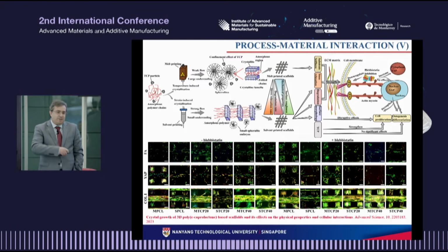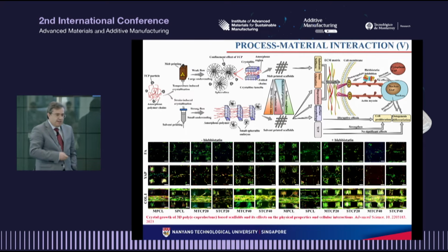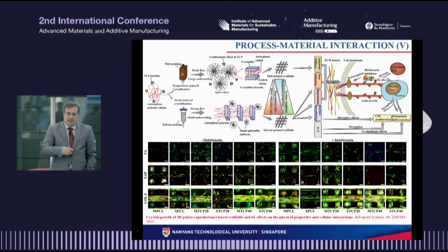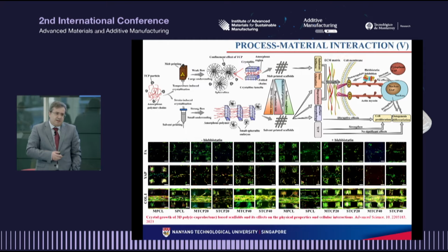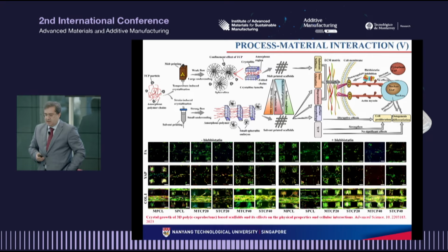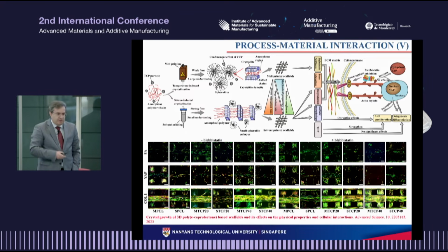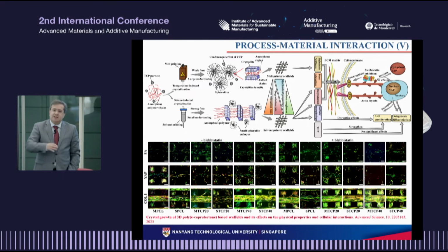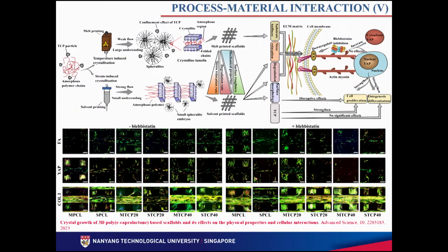While in the case of the scaffolds printed using the solvent printing strategy, they exhibited high surface roughness, fast degradation and stress relaxation. And this fast degradation and stress relaxation created a more dynamic environment that promotes an early stage osteogenic behavior. So totally different mechanisms, same materials, same architecture, but because we change the microstructure, we induce a different performance.